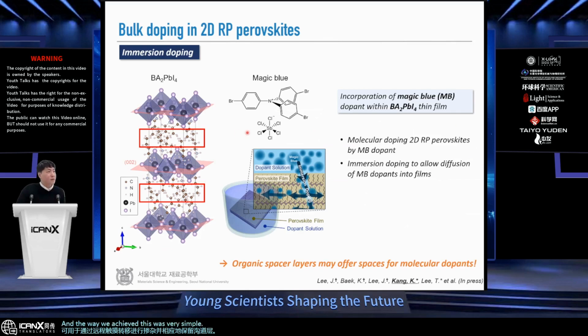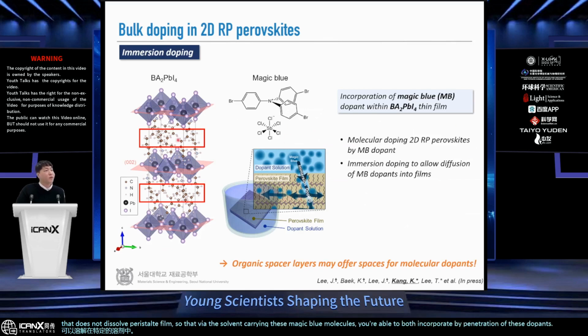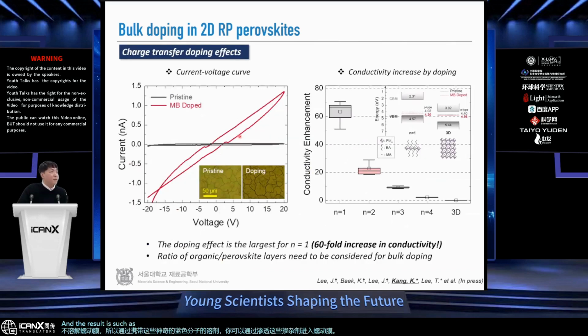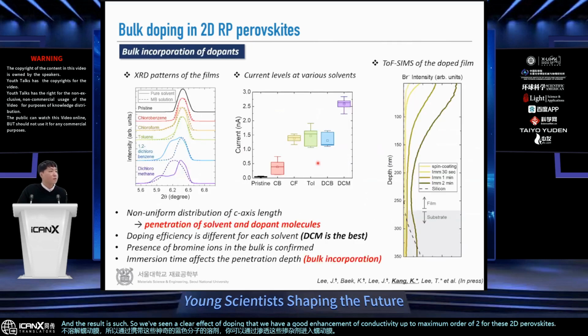And the way we achieved this was very simple. We used this strong molecular acceptor, magic blue, which can be dissolved in a particular solvent that does not dissolve the perovskite film, so that via the solvent carrying these magic blue molecules, you're able to bulk incorporate these dopants by penetration into the perovskite films, into these inactive areas of transport. And the result is such, we've seen a clear effect of doping, with a good enhancement of conductivity up to a maximum of 2 orders for these 2D perovskites via bulk doping, we believe for the reasons as